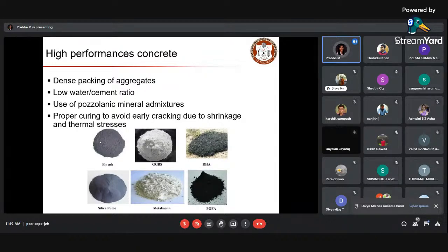We use such materials to help densely pack the aggregates, so that there is something called pozzolanic reactivity, or pozzolanic reaction. These materials in general have some reactive silica or alumina, so that when it gets in contact with calcium hydroxide in the presence of water, that produces additional CSH gel. That CSH gel will help enhance the strength, and that product will help fill up the additional pores. The final material of these SCMs will also act as fillers, so that your matrix will be much denser.